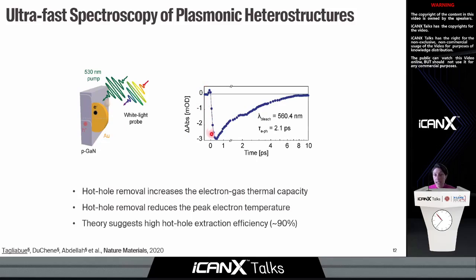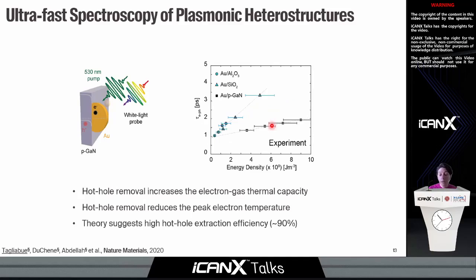Again, the signal is a transient signal. In this case, it's a pronounced bleach at the plasmon resonance and then a recovery time. And the recovery time allows us to extract the electron-phonon coupling time for the system. What is important is that the electron-phonon coupling time depends on the peak electron temperature during the thermalization of the electron gas.